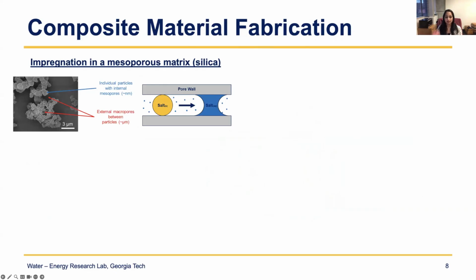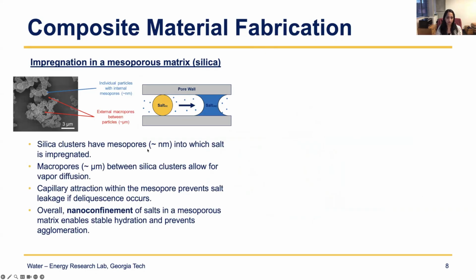And the silica has pores that are very small, so nanometer size pores or mesopores. If you put salt into mesopores, if the salt forms a solution, it cannot leak out of the pores because of capillary attraction that keeps it within the pores. And so the salt remains within the mesopores of the silica.